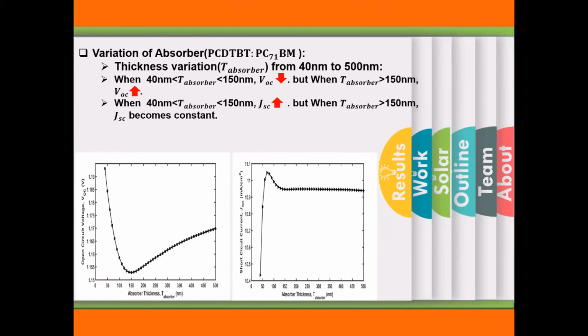We can see that when the thickness of the absorber is between 40 nanometer and 150 nanometer, the open circuit voltage decreases, but when the absorber thickness is greater than 150 nanometer, the open circuit voltage increases. Then, when the absorber thickness is between 40 and 150 nanometer, the short circuit current density increases, but when it is greater than 150 nanometer, the short circuit current density becomes constant.